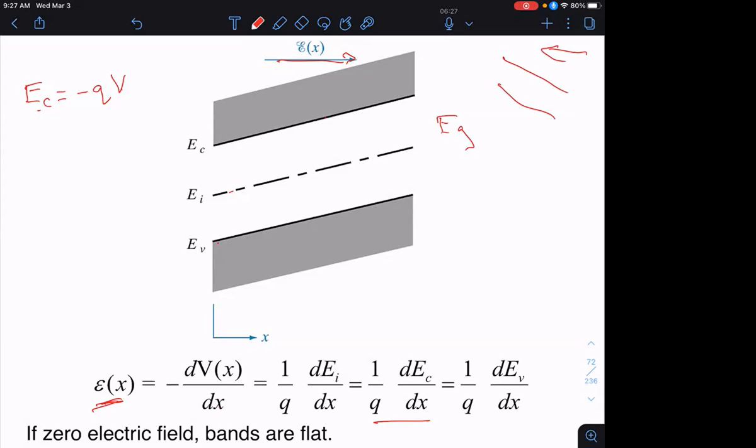So once again, if I consider the electron, say over here, it's got 0 kinetic energy, it sees a force to the left, it moves, and it gains kinetic energy from the electric field. But then every now and then, it might bump into a defect somewhere over here, say, and it may lose all or part of its energy. Slows down. Then it moves, gains some kinetic energy. Maybe over here, there's another kind of defect, loses part of its energy. So these are the collisions that the electron encounters. It's not the electron bumping into the periodic arrangement of the atoms themselves.